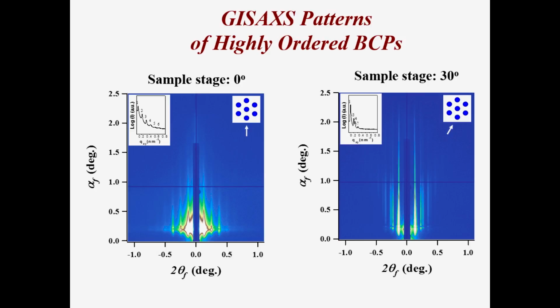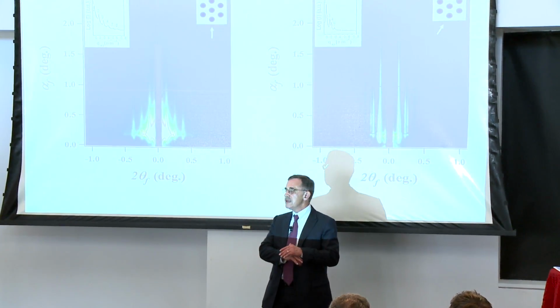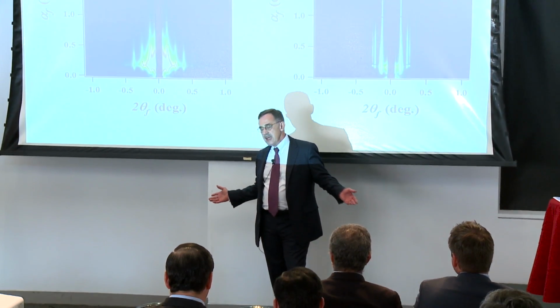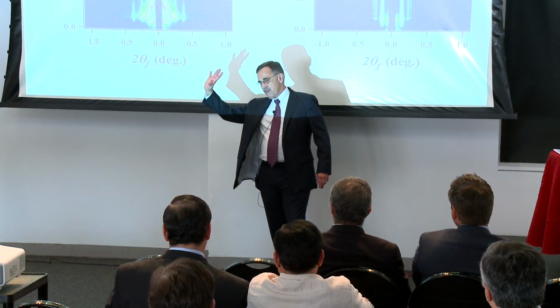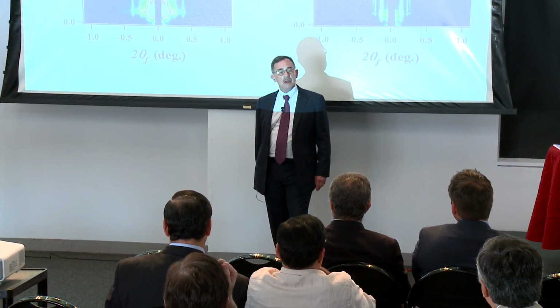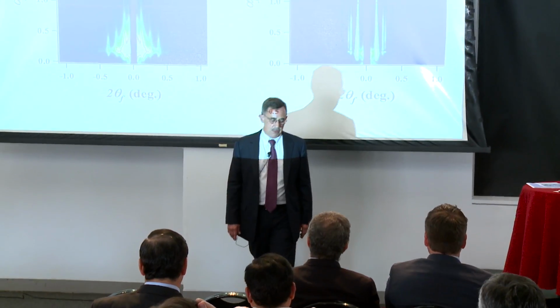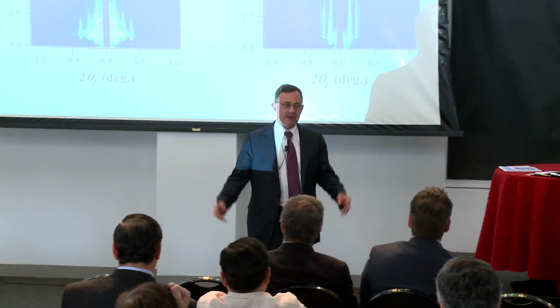And if I do that, I should see, as we see here, a first, a second, a third, a fourth, a fifth, a sixth, a seventh, and eighth order reflection. This is a substrate that is inches in size. I give you a hexagonal array, and I look right down the axes. I rotate it 30 degrees, and now we look down the 1-1 plane, and you see the reflections that are characteristic of the 1-1 plane. Wow. I see money rolling in. This is great. I won't have to work a day in my life after this.